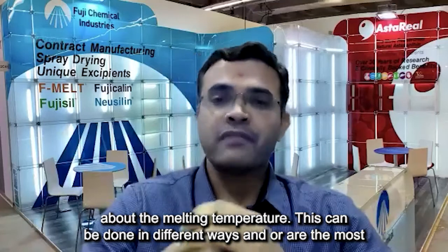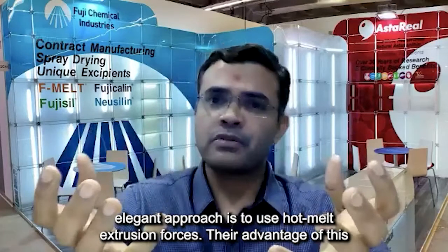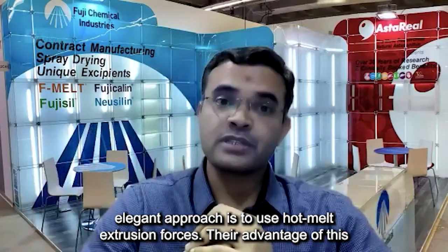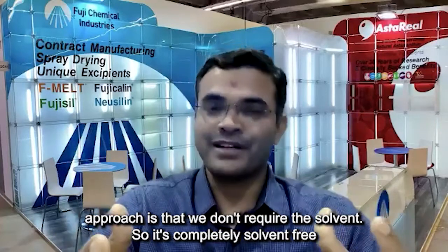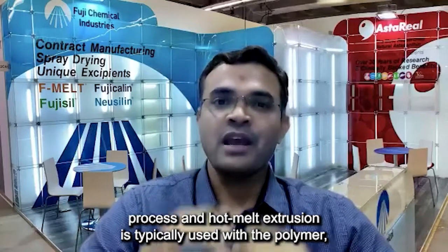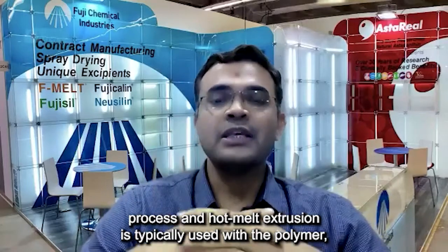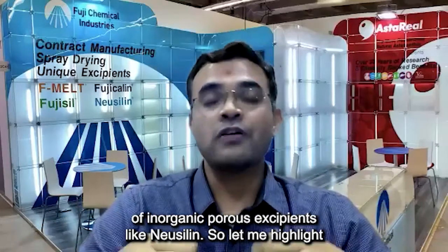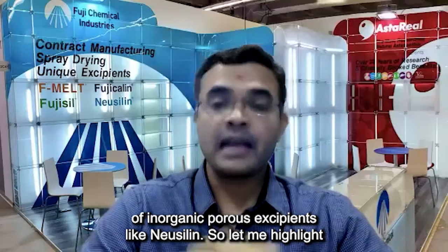This can be done in different ways, and the most elegant approach is to use a hot melt extrusion process. The advantage of this approach is that we don't require the solvent, so it's a completely solvent-free process. And hot melt extrusion is typically used with a hydrophilic polymer. But of course, in this case, we are talking about the use of an inorganic porous excipient like Neusilin.